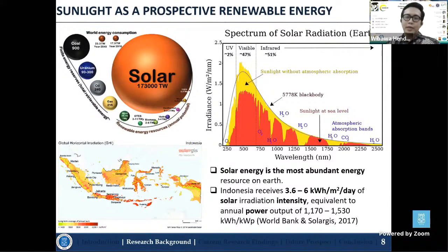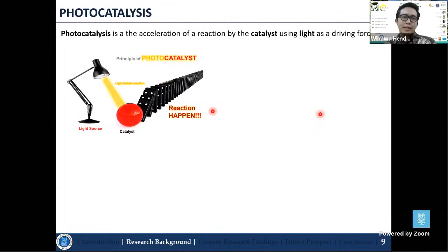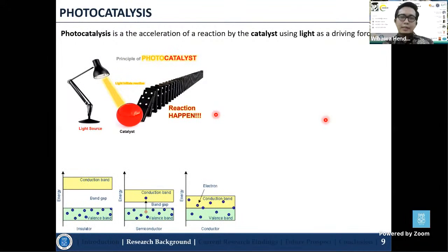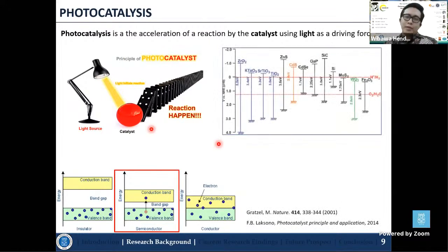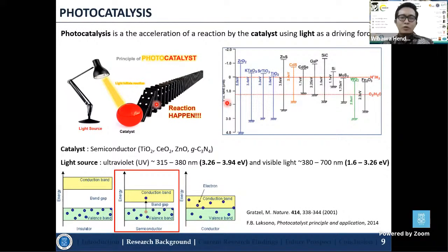So then what are the principles and mechanism of photocatalytic technology? In principle, photocatalysis can be defined as the acceleration of reactions by using a catalyst and light as a driving force. The material commonly used for photocatalysis is semiconductors, since they have a band gap energy in the interval of 1.5 to 4 electron volt, while insulators and conductors cannot be used due to their large band gap and the overlapping of the conduction band and valence band, respectively. Among the semiconductor catalysts, titanium dioxide, cerium oxide, zinc oxide, and carbon nitride are the most commonly used catalysts for several applications. But in this presentation, I will focus on the titanium dioxide-based catalyst.